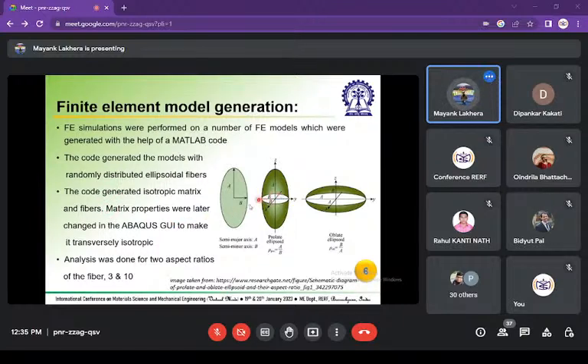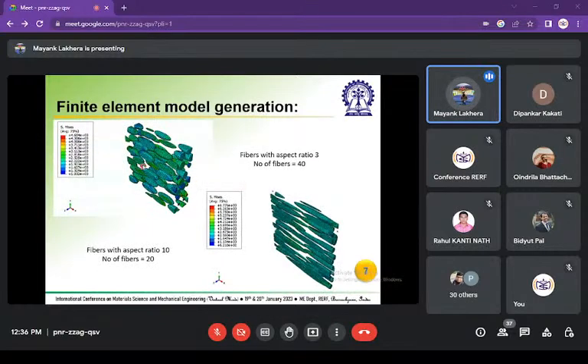We have tested it on Abaqus, and we have done the analysis for two aspect ratios, that is 3 and 10. Aspect ratio is basically A by B, where A is the semi major axis of the ellipsoid and B is the semi minor axis of the ellipsoid. So these are the finite element models we have generated. These are the fibers with aspect ratio 3, and the number of fibers in this model was kept at 40. And this model is for aspect ratio 10, and the number of fibers in this model was kept at 20. This is because there was difficulty in meshing if we kept the number of fibers in this model at 40, so we reduced the number of fibers in this model.